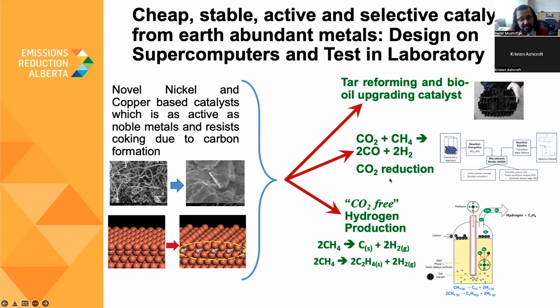The other area is CO2 reduction, hydrogenation of CO2, and methane dry reforming, where you combine the two greenhouse gases, CO2 and methane, to form a mixture of carbon monoxide and hydrogen, which is called synthesis gas, which can be used in the Fischer-Tropsch process to produce liquid fuels. Here, nickel is again a very popular catalyst, but suffers from deactivation because of carbon formation. And we developed a novel nickel-based catalyst with some modifications to nickel to avoid that carbon formation.